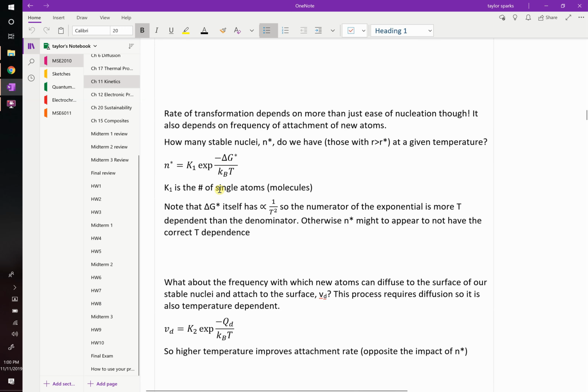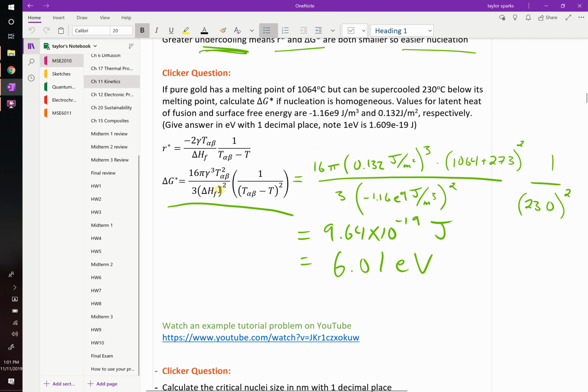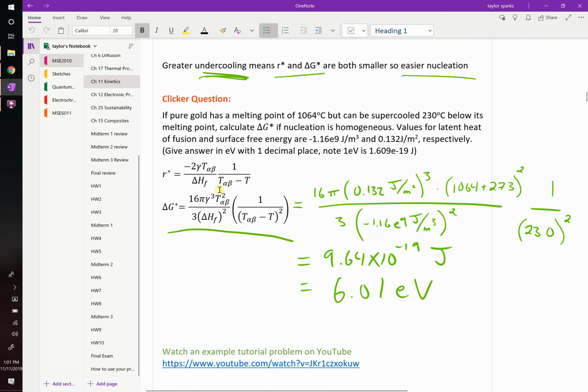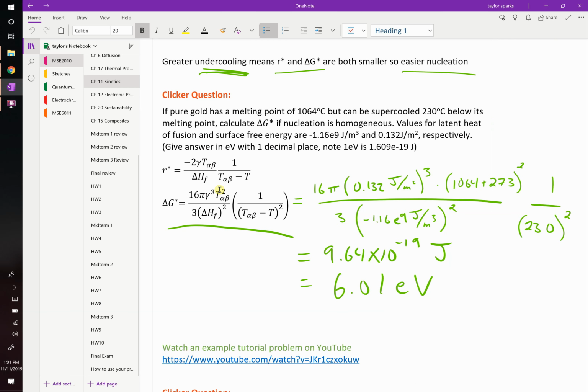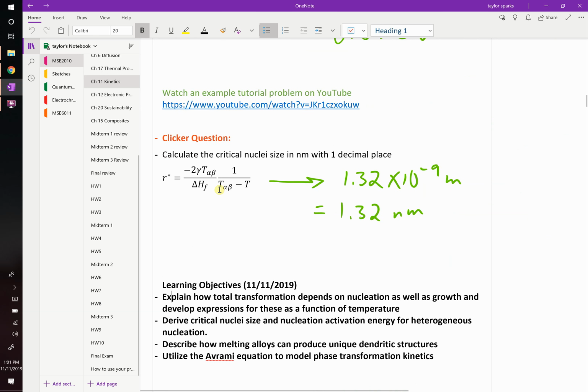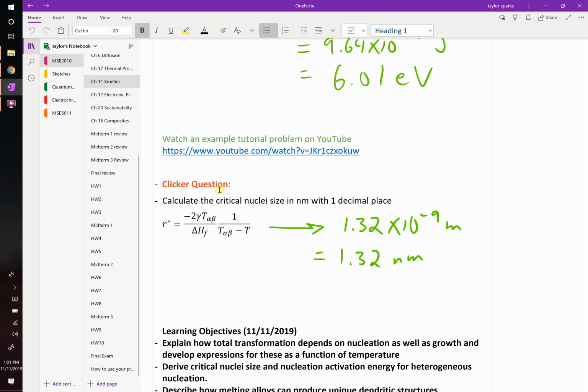So we left off last time, and the last thing we covered is we came up with some slick equations that told us, as a function of materials properties like enthalpy, how far you are below the melting temperature, that's the degree of supercooling, and the surface energy, we could calculate the activation energy necessary to cause nucleation to happen, and we could also calculate the size of this nuclei, right? We did those last time. In this case, for gold, even though you already had supercooled it 230 degrees below what the phase diagram said, you still had to get a glob of particles 1.3 nanometers big. So that's lots of atoms that had to come together before it spontaneously keeps on growing. So some of these critical nuclei sizes can be fairly big, okay?